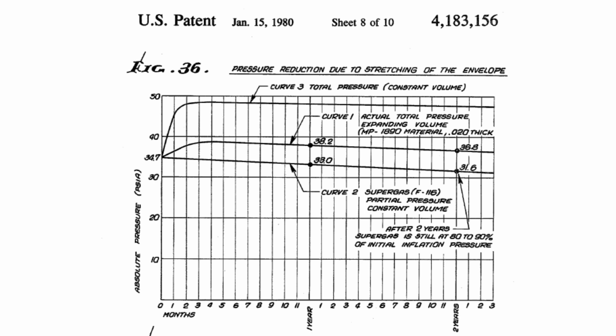The insoles are designed so that the film stretches, due both to elastic deformation and permanent set resulting from tensile relaxation, an appropriate amount so as to mitigate a portion of the self-pressurization pressure rise. The control of volume growth is obtained through appropriate matching of 3 design parameters, i.e., modulus of elasticity of the material, thickness of the material, and the overall stress level. The stress level is a function of the type of insole pattern, i.e., tubes, Figs 1 and 16, or dots, Figs 17, 20, 21, 22, and the geometric size of the air passages.